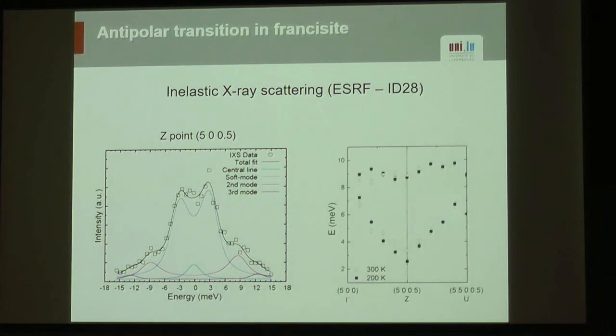It's a bit frustrating because we are very much resolution limited by the equipment, but this has to do with the technique. Also in terms of dispersion, we measured the phonon dispersion along two directions, especially between gamma and Z. And the important fact here is that this soft phonon is really found to harden when you approach gamma.